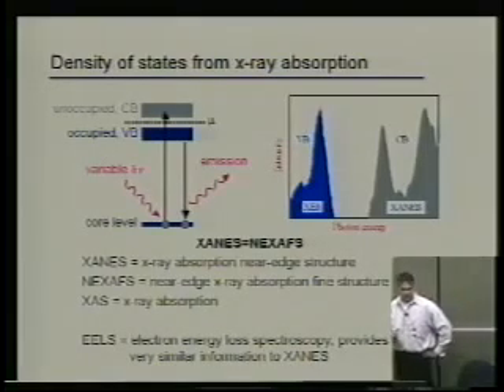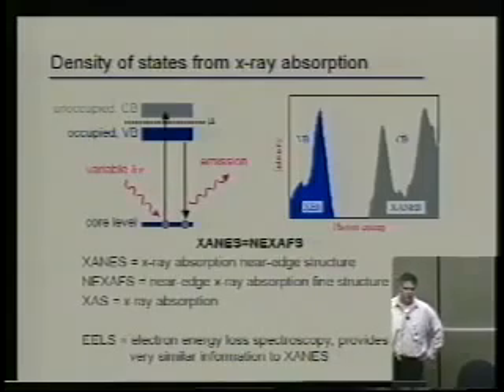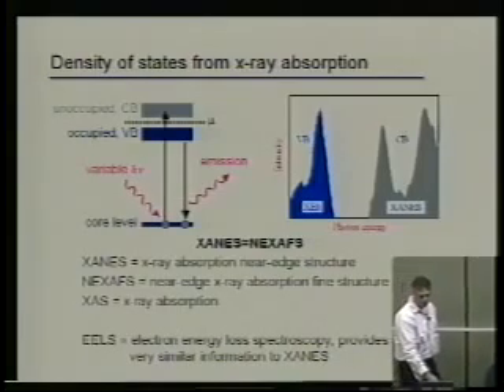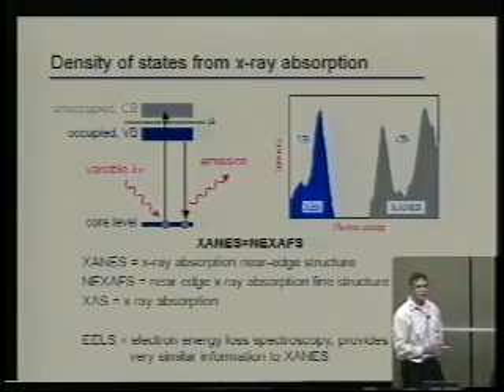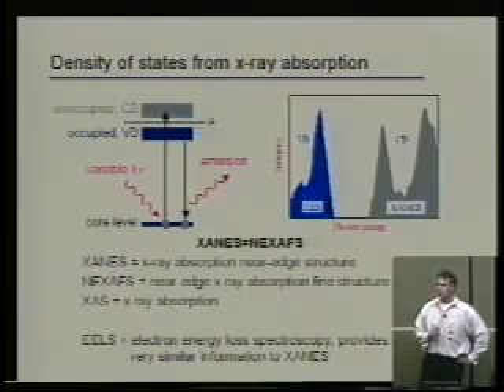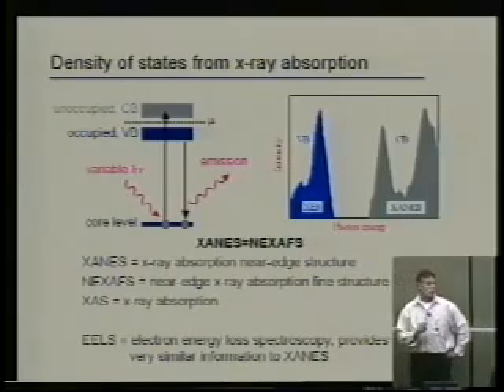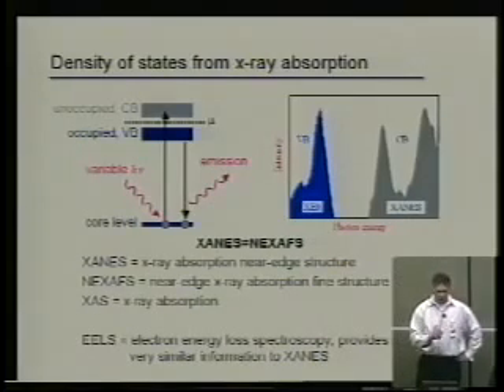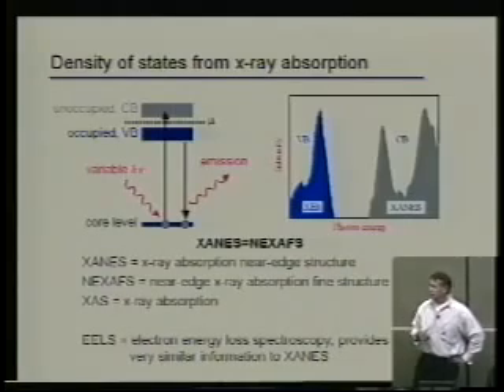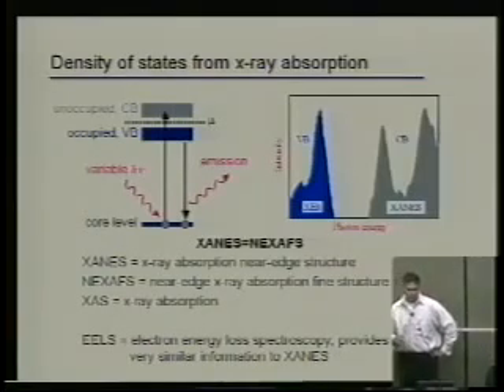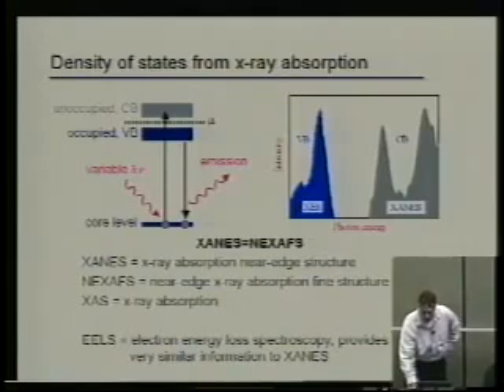Traditionally, these terms have been used interchangeably, but in reality, NEXAFS usually means light elements, so carbon, oxygen, nitrogen. It's interesting to note that both of these processes need a core hole to start. In this case, the X-ray generates the core hole, but you can generate the core hole with an electron beam also. You can do similar experiments in a TEM where you generate the core hole with an electron beam, and again, an electron falls down from the upper levels, and you can map out the empty states in that manner.